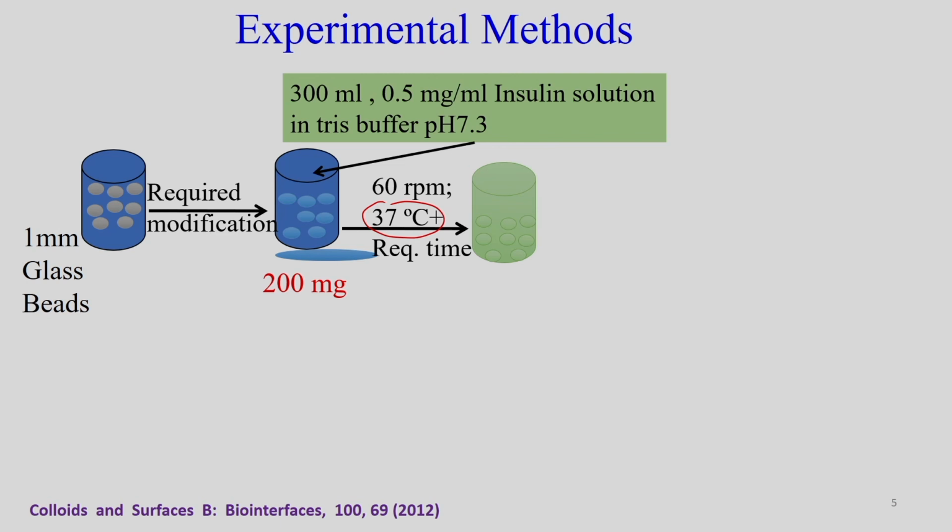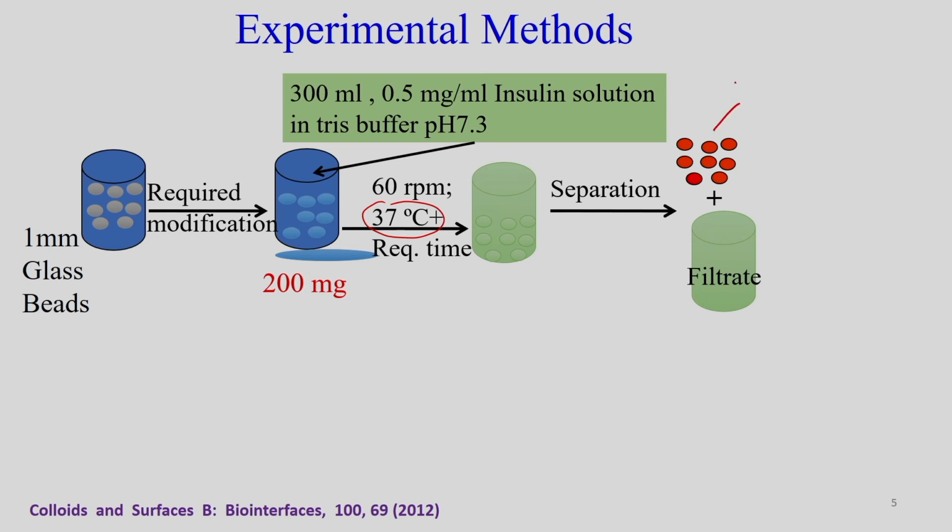So, at 60 rpm and 37 degrees centigrade it was incubated for different time intervals. After a particular time we have to separate it. So, we have separated the beads and the filtrate, the remaining solution.